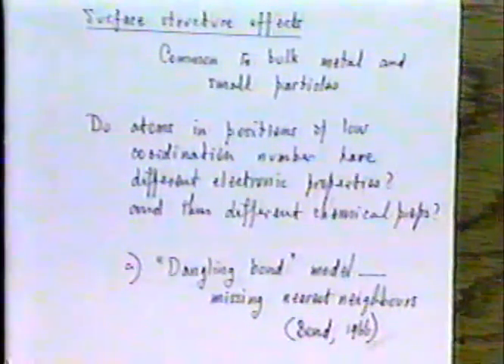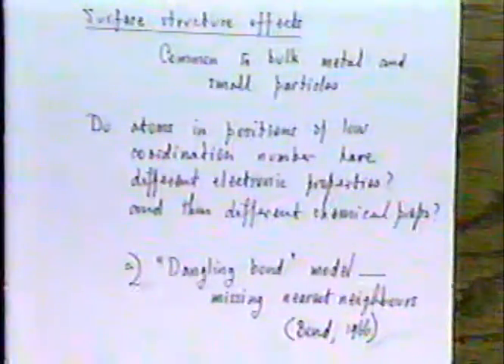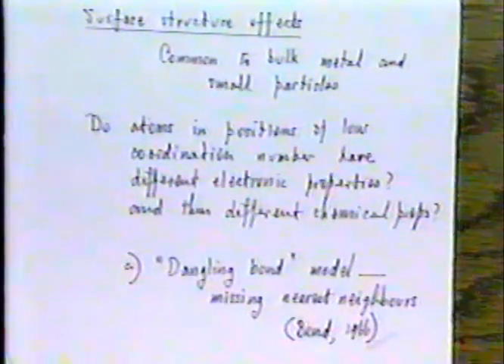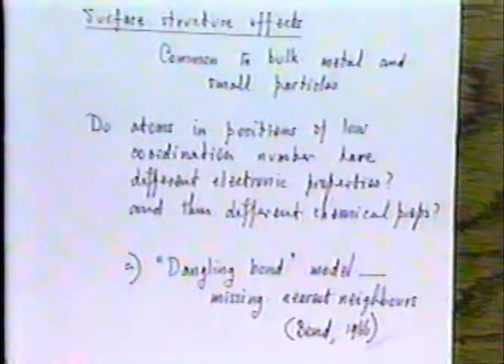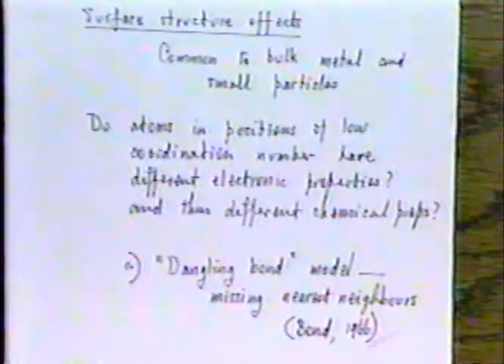And the proposition was that if an atom had a number of dangling bonds, these could be used in adsorption processes. And there is some truth in this. It is possible to provide some rationalisation of adsorption phenomena from a dangling bond approach. But it really doesn't come to grips with the quantum chemistry of bonding at metal surfaces, and that latter is a problem which, although it's being worked on still at the moment, is not really something that's been adequately solved, at least to the extent which it can be used predictively in the manner that valence theory can be used predictively for ordinary molecules or the like. So I draw your attention to the dangling bond model. It may or may not be useful.